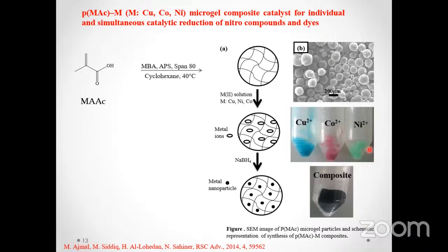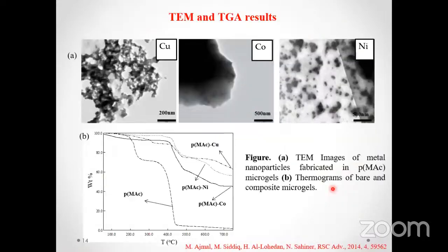As the metal ions were loaded in the hydrogel networks, the color of the metal ions was imparted on the hydrogel. And when these metal ions were reduced by using sodium borohydride as a reducing agent, they were converted into the metal nanoparticles, and the appearance of the black color in the hydrogel network was an indication of the formation of metal nanoparticles inside the hydrogel network. However, the formation of the metal nanoparticles was further confirmed with transmission electron microscopy.